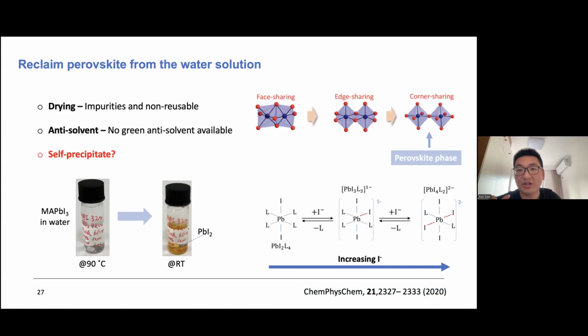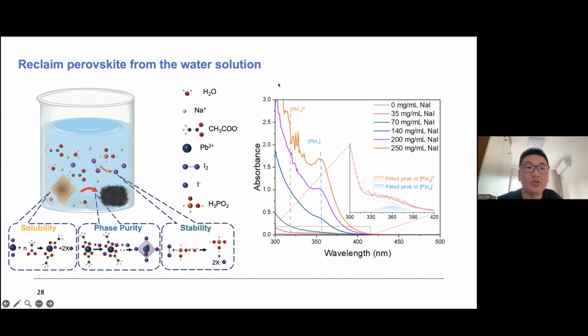So if you have the edge-sharing structure in the solution, what you will get from the solution will be the lead iodide. But the perovskite phase is this kind of corner sharing. If you have this corner sharing, only one iodide ion is shared by two lead ions. So if you want to get the perovskite phase, you have to first make the lead coordination corner sharing. And the key to control the sharing mode is to supplement the iodine ions inside. If you increase the iodine ions, you can control the sharing structure from edge sharing to corner sharing. So then we add the third additive, that is sodium iodide, as we show here.